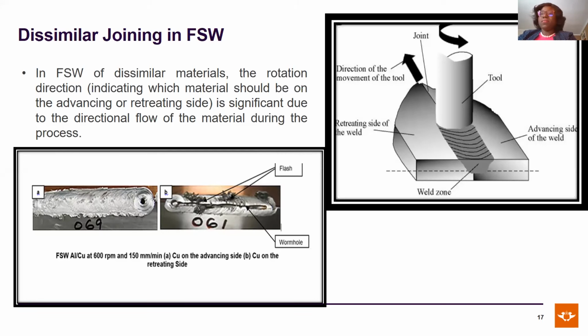So I did a fundamental research then in 2008 to ascertain where a particular material should be placed among two dissimilar materials. So in the case of aluminum and copper, if you look at the weld that I'm showing here on the left-hand corner of my slide, you will see weld 069, which has copper on the advancing side, and then aluminum on the retreating side. That is weld 069. While on the right-hand side, I have placed copper on the retreating side and aluminum on the advancing side. You will visibly see the heavy flash and the wormhole that was produced. Now, this is a basic research in trying to determine where a particular material should be placed.